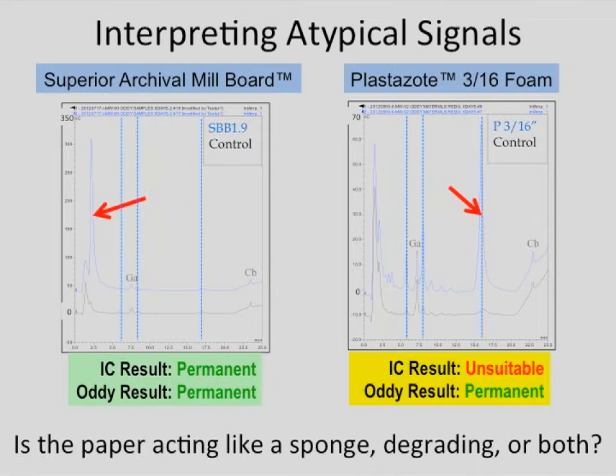In this case, a millboard was showing a very large early eluting peak. And in the case of Plastazote, we got lots of peaks initially that were large, and then an enormous peak overlapping where we were analyzing. Again, we don't know what that is, what that peak's supposed to be, and we're theorizing that these are monosaccharides, but we don't know what these early eluters are.